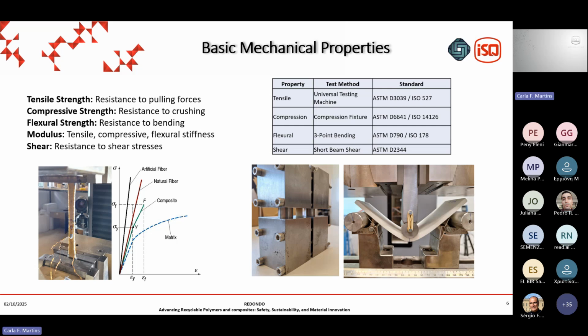Typically, we need for compression some special devices, special jigs to prevent buckling of the specimens, which are usually also instrumented with strain gauges in their gauge length to monitor eventual buckling of that specimen and sort of artificial reduction of the properties that would affect our evaluation of the composite.